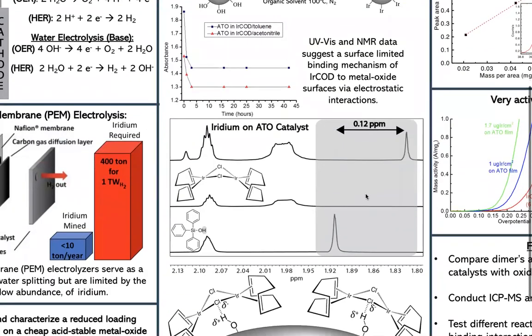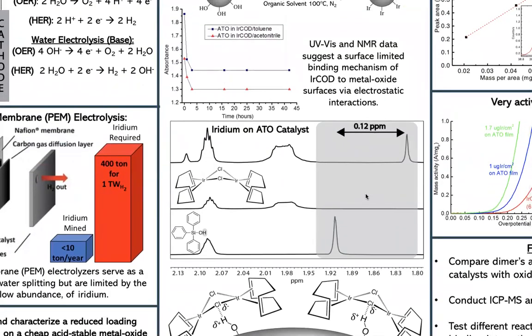Then, using a model metal oxide, triphenylsilanol, nuclear magnetic resonance spectroscopy was used to track the hydroxyl hydrogen of the metal oxide before and after reacting with the IrCOD. In the reactive product, the presence of this hydrogen was still observed but was slightly shifted, suggesting that our iridium dimer is likely binding through electrostatic interactions as opposed to displacing the hydroxyl hydrogen.